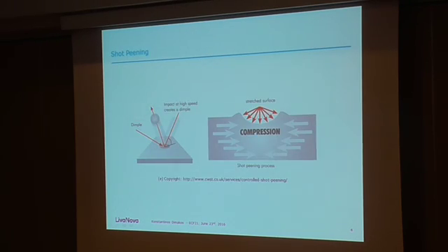A few words about shot peening. Probably most of you will know about this process. It's a cold working mechanical surface treatment in which through the impact of spherical shots that create a dimple on the metallic component. This will create compressed residual stresses beneath the layer that's being peened. Hence, this will tend to increase the fatigue life of the material.